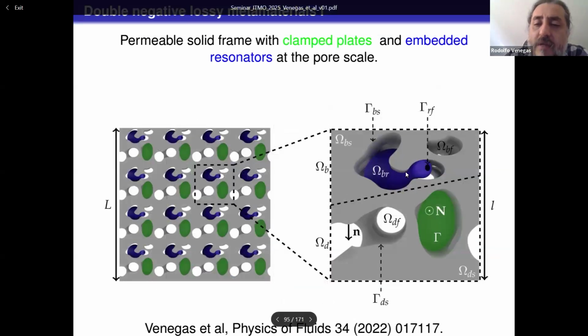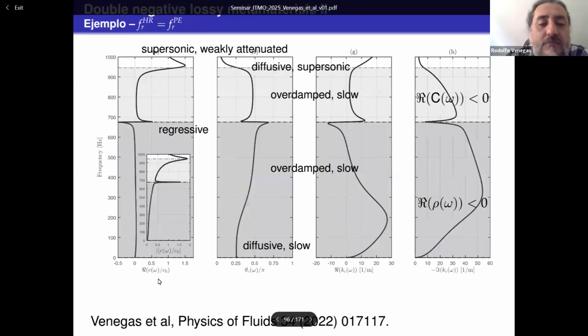When we combine permeoelastic media with embedded acoustic resonators, we can see a very interesting phenomenon. We can match the resonant frequency associated with the acoustic resonator with the resonant frequency associated with the plates. Below this frequency, the real part of the effective density is negative, and the real part of the compressibility is negative above this frequency. At very low frequencies the wave is diffusive and very slow. It's overdamped and slow, and it becomes regressive at the frequency where these two frequencies are matched. Then it's overdamped and slow again, diffusive, and supersonic and weakly attenuated above this characteristic frequency. So it's a very rich phenomenon.